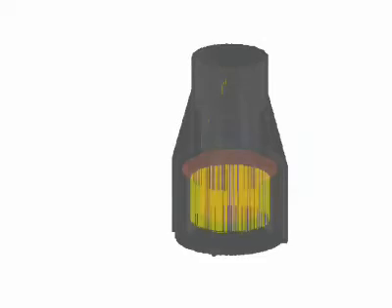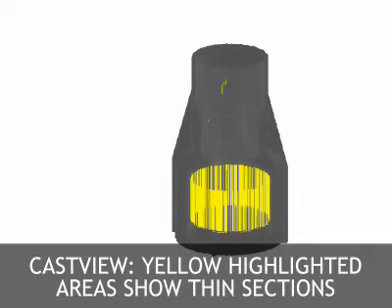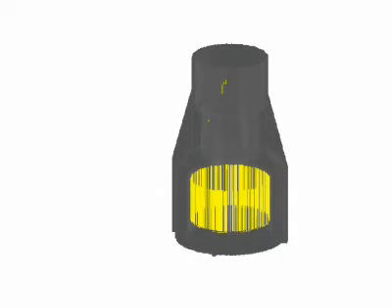In addition, cast view is capable of detecting thin die sections, sometimes called bad steel conditions. Sometimes design geometry may cause a thin die section or sliver-like die steel condition. These thin die sections may fail prematurely and will decrease the die life or require extensive and costly die maintenance.